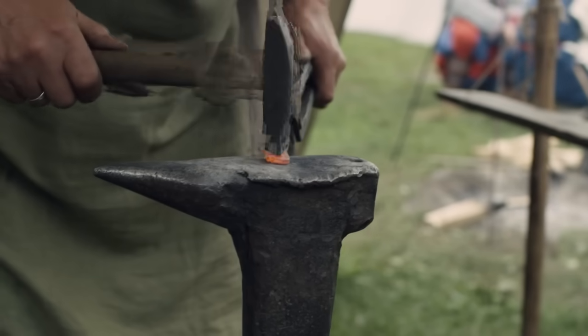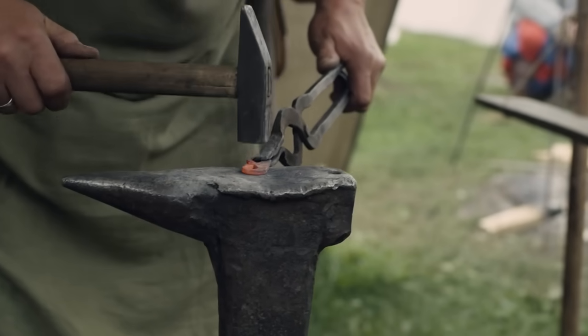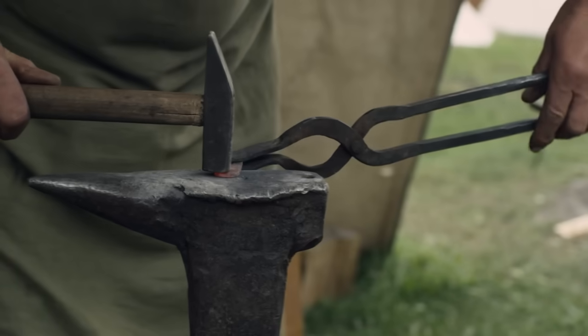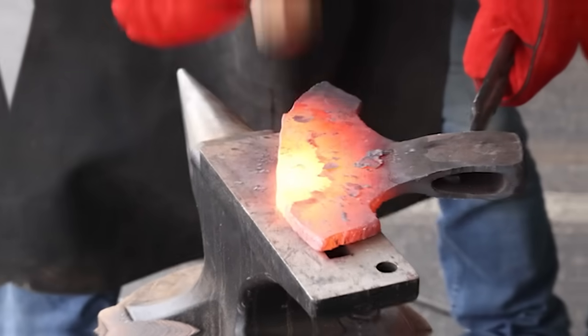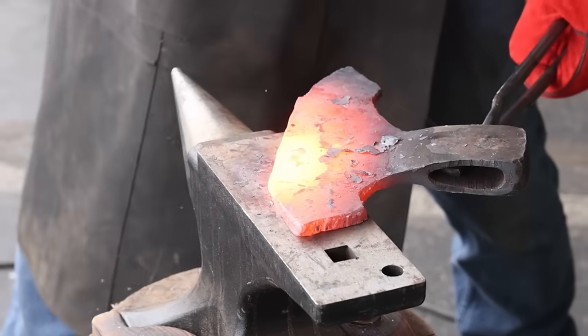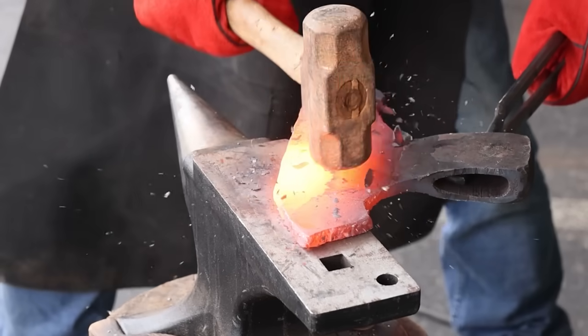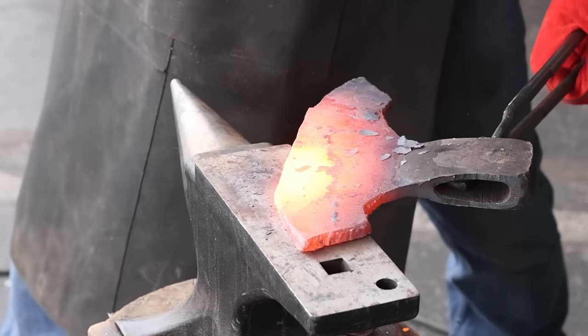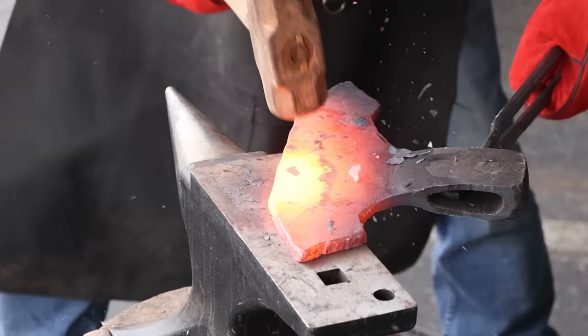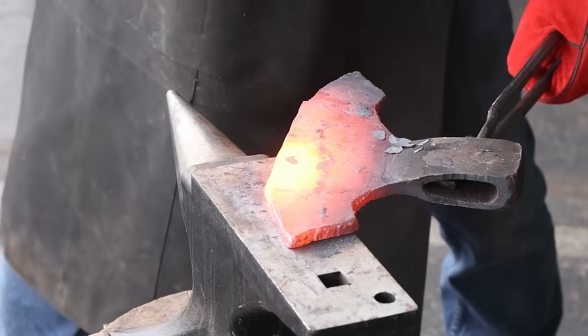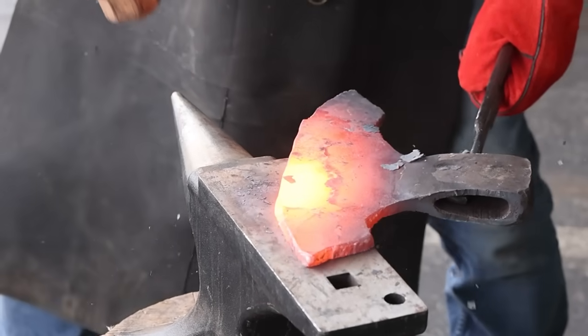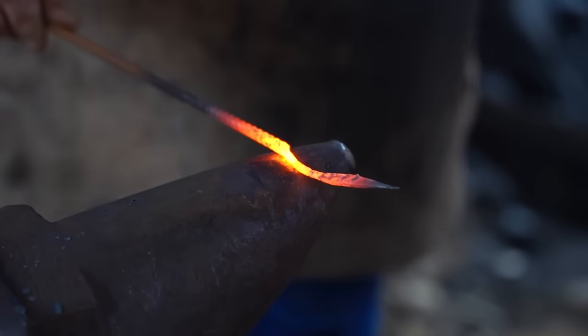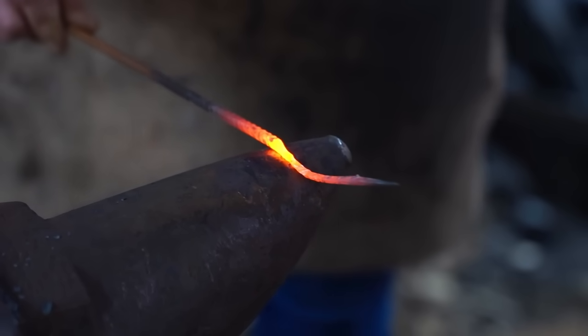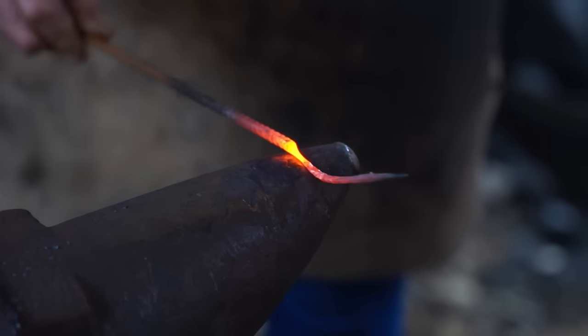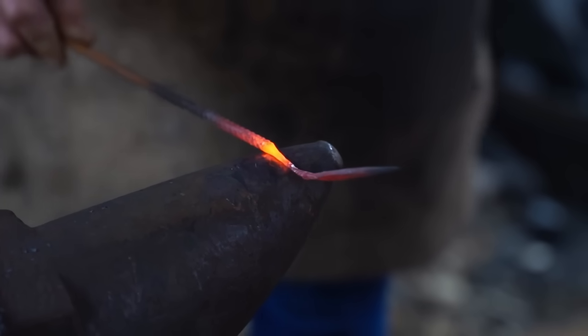Every hammer blow welded the iron particles together more tightly. Every reheating allowed carbon to redistribute. The constant working eliminated internal stresses and micro cracks. The smith was not just shaping the metal, he was fundamentally improving its internal structure with every strike. This took time. A single axe head might require 3 days of repeated heating and hammering. A modern factory stamps out the same shape in 3 minutes. We chose speed. They achieved permanence.